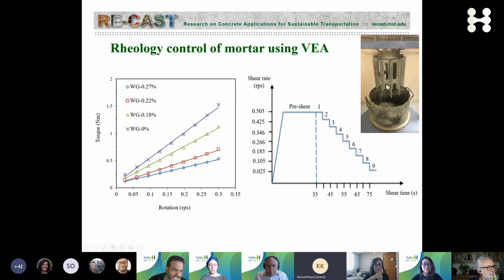We have a rheometer, which is basically a mixer, mixing concrete at different speed, rotational velocities. And at each of these velocities, we're measuring a torque. And when we plot the curve, we get an indication of the slope. And the slope of that curve is what we call plastic viscosity. And the interception of that curve with the vertical axis is what we call yield stress. So yield stress is the resistance to flow before flow starts, and the viscosity is the resistance once the flow occurs. So higher viscosity can be associated with, for example, molasses, honey, versus lower viscosity, orange juice, Coca-Cola, or water.